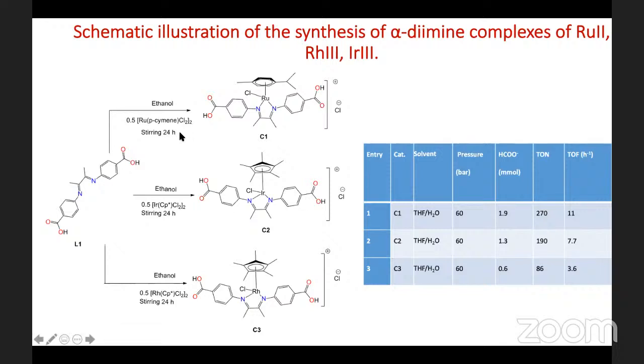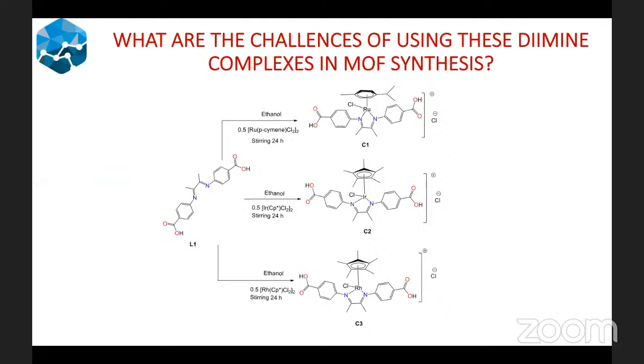So in that case, we tried to do that using different combinations of metal and solvents to make the MOFs, but we were not successful in isolating the required MOF. So what could have been the problem? We tried the traditional methods that are used in synthesis of MOFs, and especially the most appropriate method, if you want to isolate your single crystals, is solvothermal. And it was very frustrating because we didn't isolate the MOFs.